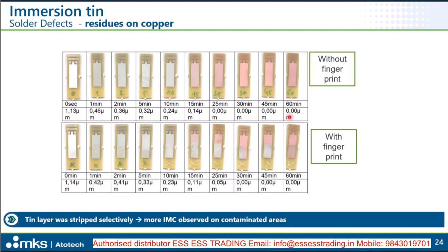We did a test to check the impact of contaminations on copper on the IMC growth, and that was actually a pretty simple, but I think pretty obvious result. What you see here is test coupons. On the top, clean coupons which were properly cleaned before the immersion tin plating, and on the bottom there are coupons where a fingerprint was applied on the coupon, and then the immersion tin was plated on top. And then the immersion tin was removed by stripping. And what you see here in the pictures are the conditions after different times of stripping. So we are stepwise stripping the tin layer off to see when we can reach the copper.